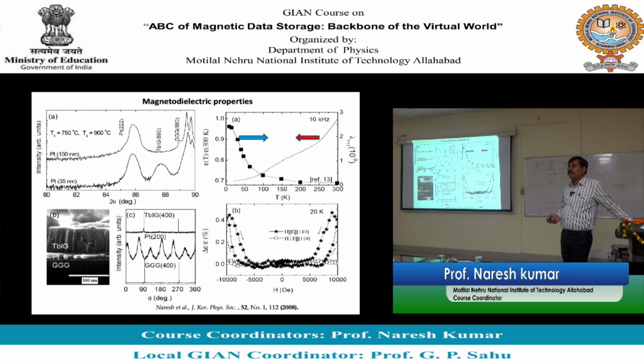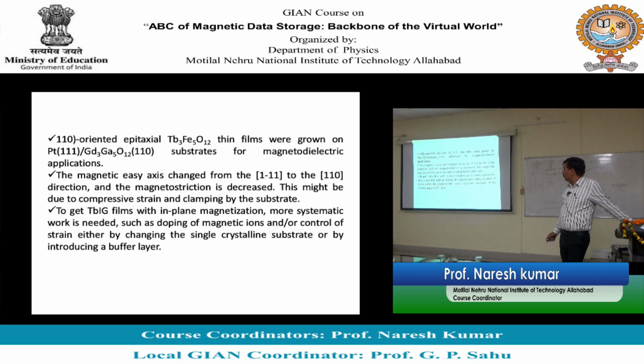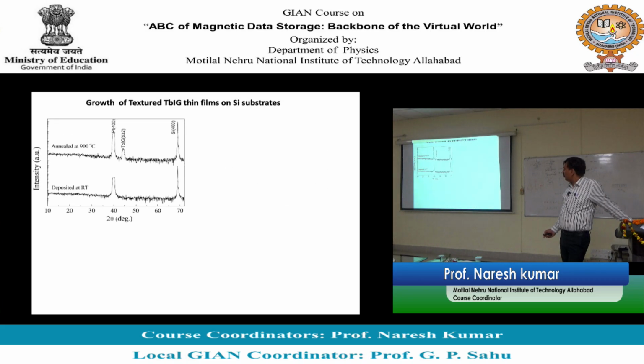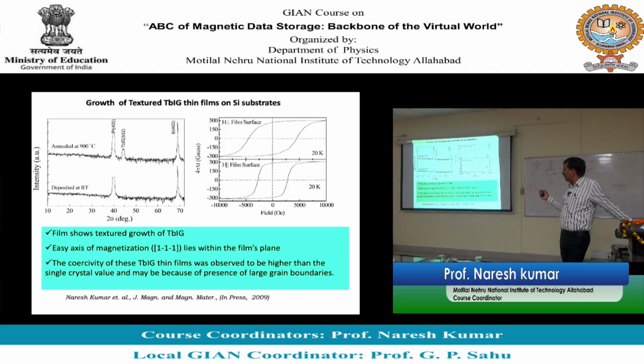It was a difficult experiment, but we did it. The unfortunate part, as I said, is that we were expecting 111 to be in plane, but we couldn't see that. But even then we got some amount of change in dielectric constant. Again, we tried one more thing; maybe I can rush it. We have grown the same film, and this was very interesting. I keep telling my students that with just one experiment, with just one film, we published this paper.